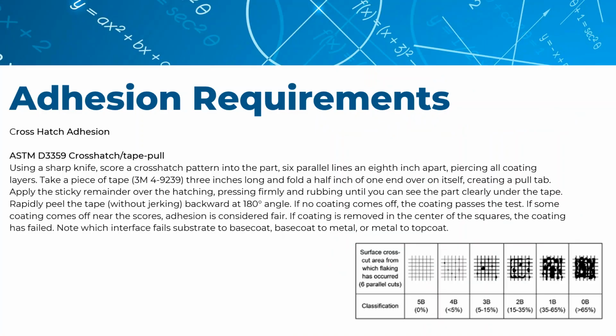Another portion of adhesion requirements, and this is used more on highly durable coatings like diamond-like carbon or dip-applied polysiloxane films for polymeric optics, is a crosshatch adhesion test. Just as it sounds, the tester would take a razor blade and score the coated optic. Coated optic is scored, then you place your tape, your 3M tape, over the scored optic and pull away aggressively.